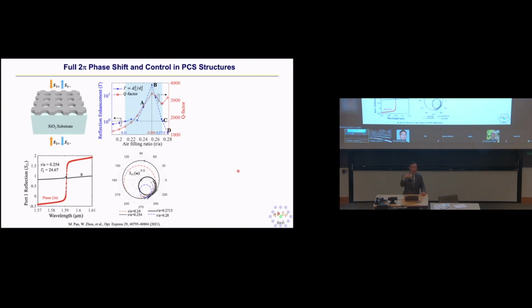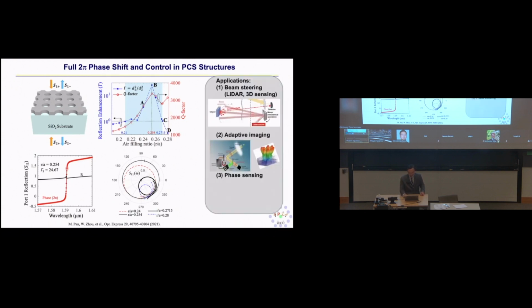One of the key issues when you do an optical phased array or beam steering is the phase tuning. So we designed some lattice structure where you can get a very good reflection, but also 2-pi phase tuning. So now, not only can you modulate the index, you can modulate your phase. That's more interesting as well. Again, that's where you can look into LiDAR, or adaptive imaging to compensate, for example, for propagation of the beam in the atmosphere, for faster beam compensation. And you can also do phase-based sensing applications.